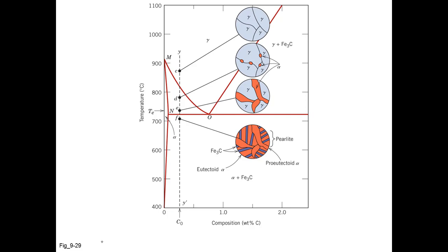In this case, we're looking at the example of the decomposition of austenite to proeutectoid ferrite and pearlite, and so we'll want to focus on this tie line just above the eutectoid temperature, and from that we can calculate the system composition and allow us to calculate the proeutectoid ferrite that forms up here at these grain boundaries.